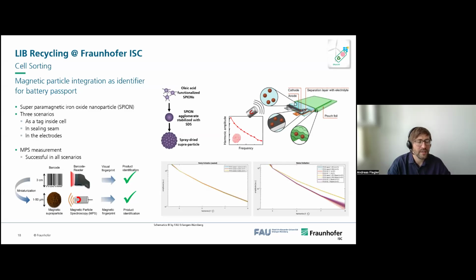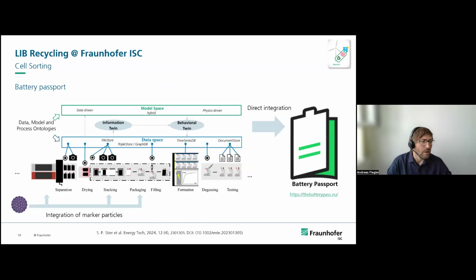And in the next step, we integrate different marker particles for different cell chemistries. With these particles, we can integrate them in different steps in our cell manufacturing. So we can integrate them in the coating of the electrodes, in the stacking, or in the packaging. And we can directly integrate them in our data space. So we have digitalized our cell production, and here we can integrate these marker particles, which are the identifier in the cell, which give access to the battery passport.